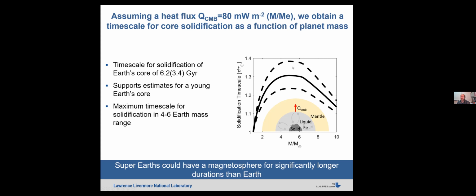And then as with the higher pressure data, what we actually find is that the solidification timescale has an interesting sort of shape to it. The solidification timescale increases pretty dramatically and reaches a maximum in the 4 to 6 Earth mass regime, and then starts to tail off as you go to higher and higher masses. So I think the takeaway here is that super Earths in this 4 to 6 Earth mass regime could have a significantly longer timescale to solidify a core, and thus a power source for a dynamo, and thus a magnetosphere.